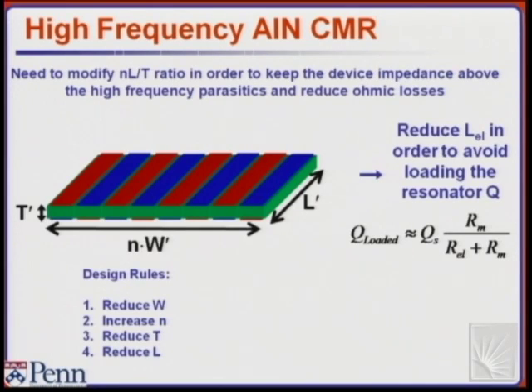So we completely moved around the aspect ratio of our device. Our device now, basically the width becomes the length, and the length becomes the width. And some people were skeptical about that solution because you're completely changing the aspect ratio of your rectangle, so you could introduce other modes. And it's actually instead a key advantage of this technology that despite the change in aspect ratio, we still get a single individual mode of vibration, a single